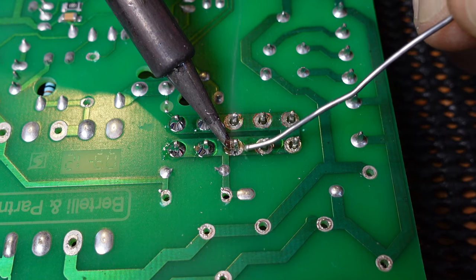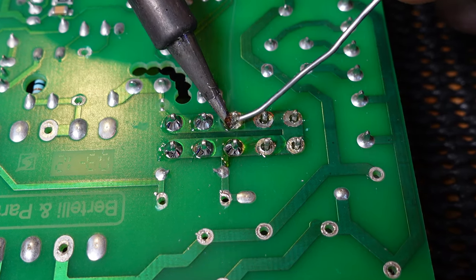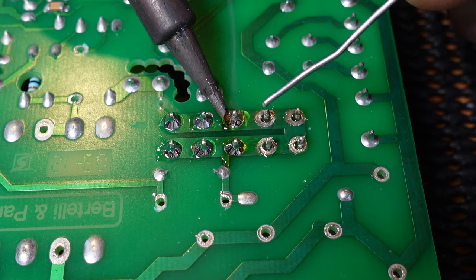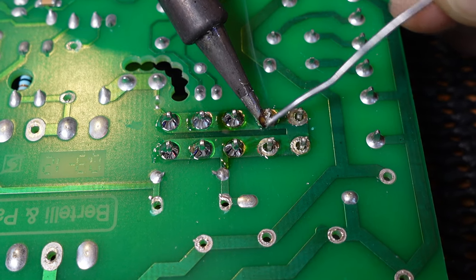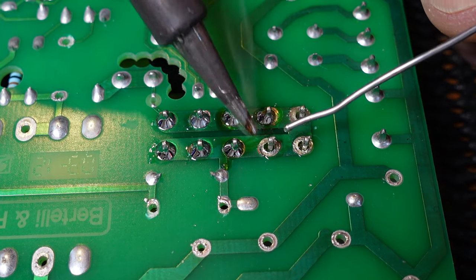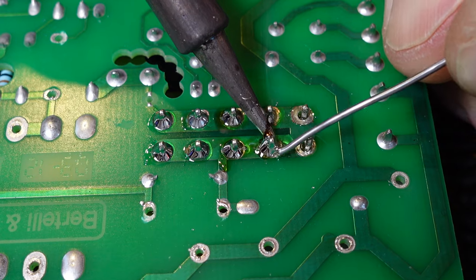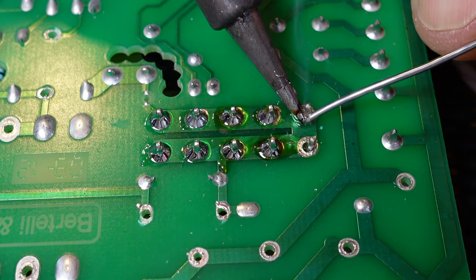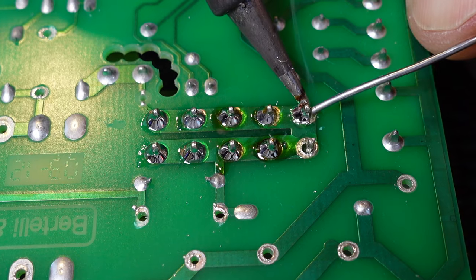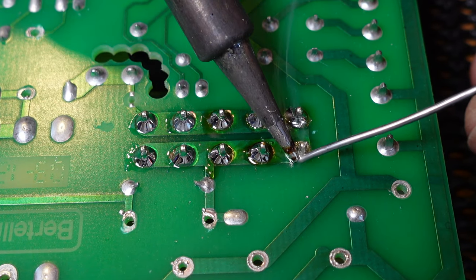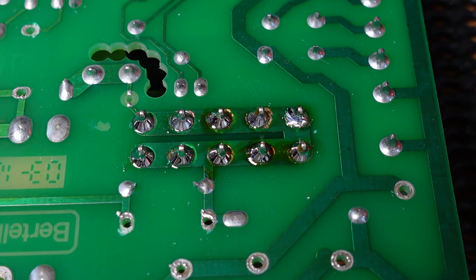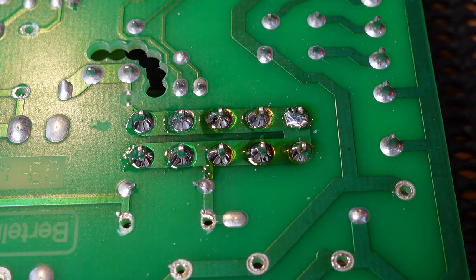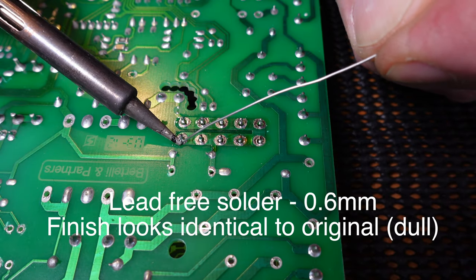You'll see now that actually the flux is a bit of an irritant. It's cooling the joint down ever so slightly so I have to linger a bit longer. As you can see, it's bubbling around. On a clean joint like that, you just don't need the extra flux. It's only more to clean off. Look at the puddles of flux left behind. That joint there looks rubbish. They're all very nice and shiny but now you've got to get rid of that flux.